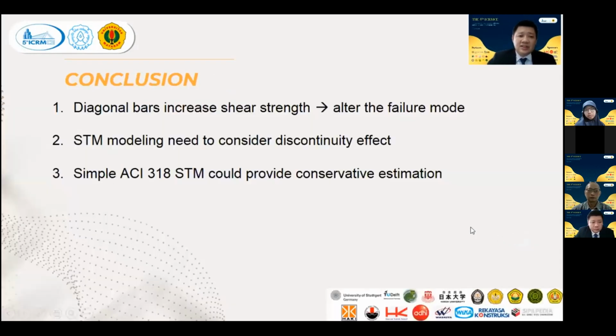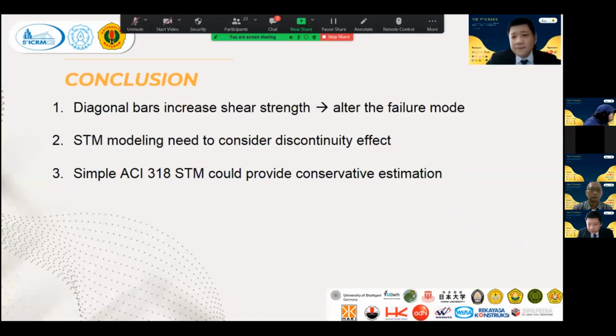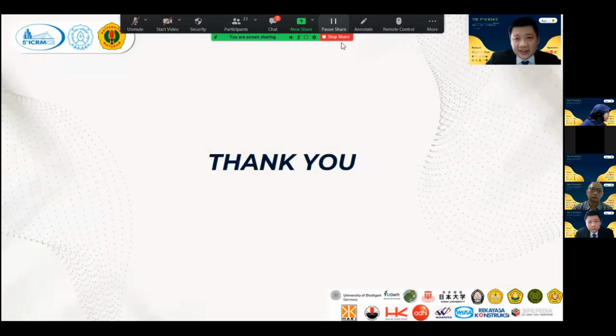So after all, our conclusion is like this. We agree that the diagonal bars increase the shear strength of the deep beams. Therefore, it will alter the failure mode. It allows a better development of the flexural behavior. Secondly, our strut and tie modeling needs to consider this continuity effect, whether it is force or geometric discontinuity. And if we take this into account in the strut and tie modeling using the ACI 318, then it still can provide conservative estimation. Thank you for your attention.